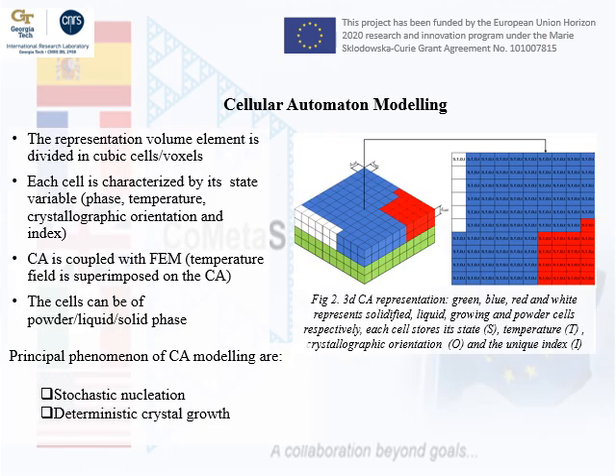Okay. In any case, as I mentioned before, we first developed a crystal plasticity finite element model for predicting the mechanical properties of the material. But as I mentioned also before, it is necessary to be able to simulate the microstructure development during additive manufacturing. To this aim, we're utilizing a cellular automaton model. And in the cellular automaton model, a representative volume element is the part of a component or the part of the material which is going to better represent the behavior or the structure of that material, and it is the minimum volume that we can consider for this aim.